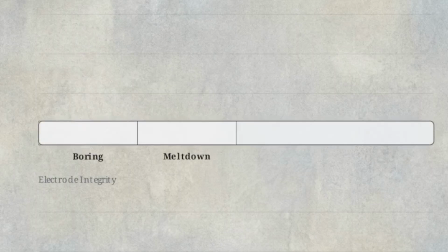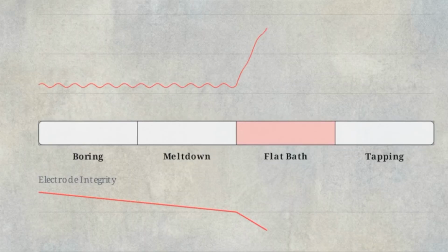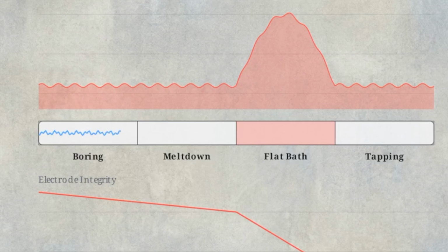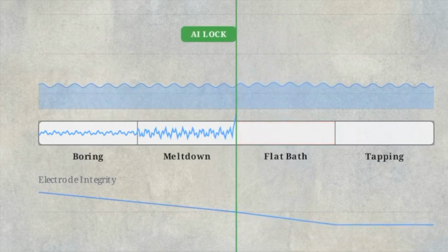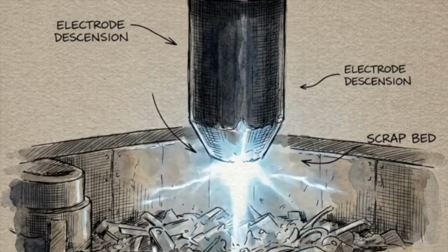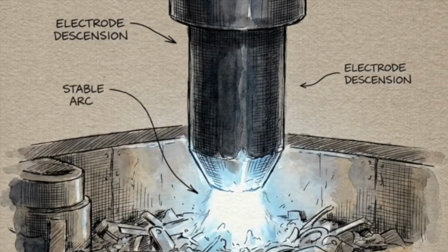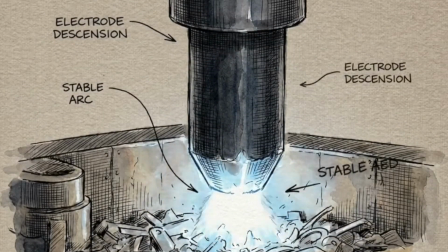This timeline illustrates the 4 phases of a furnace heat: boring, meltdown, flat bath, and tapping. Flat bath is the zone of maximum waste. Scrap is completely melted, but energy is still poured in, costing $40 to $60 a minute without adding value. The acoustic model listens for the exact moment the meltdown is complete. It then dictates the physical descent and voltage of the hydraulic mast. Adjusting the arc length dynamically based on real-time sound reduces electrode wear by 15% on every heat.